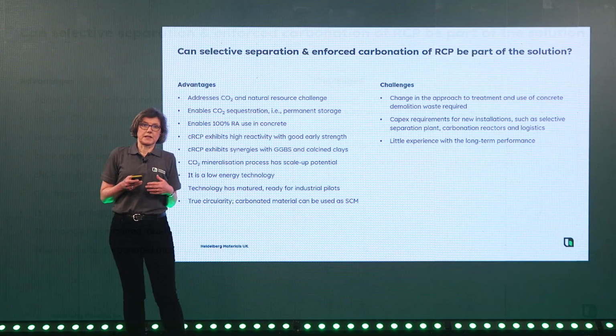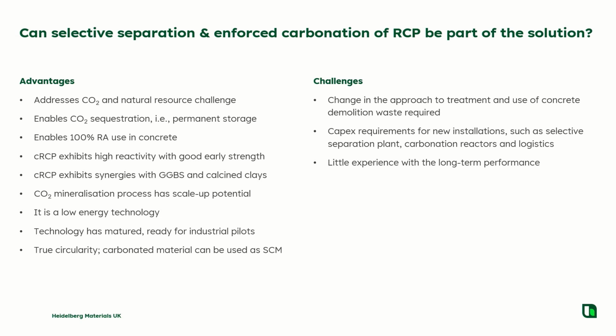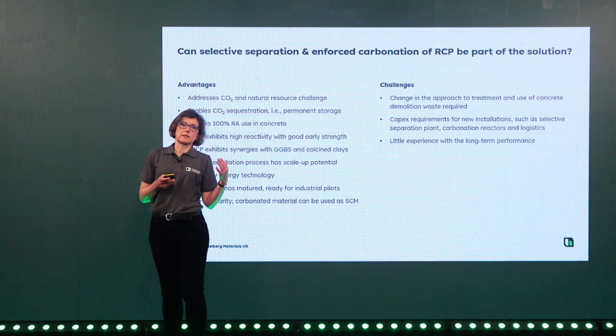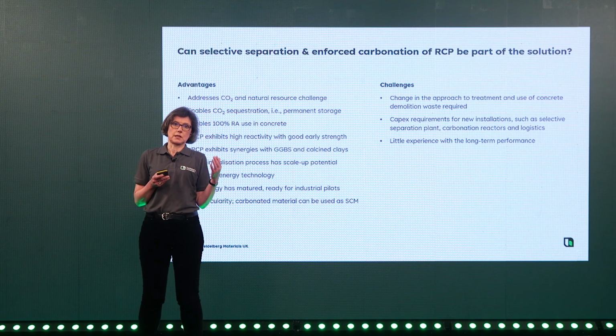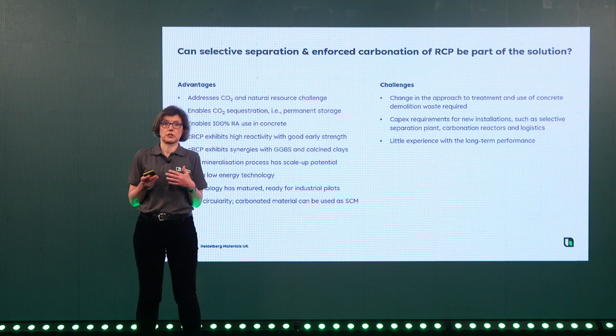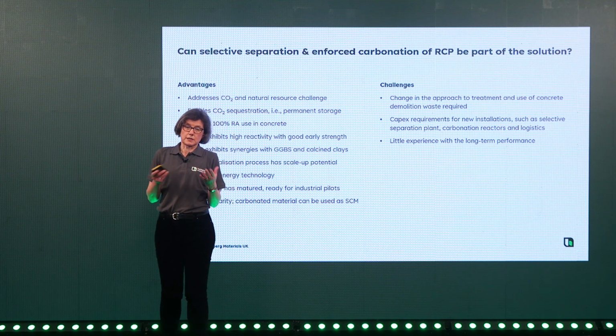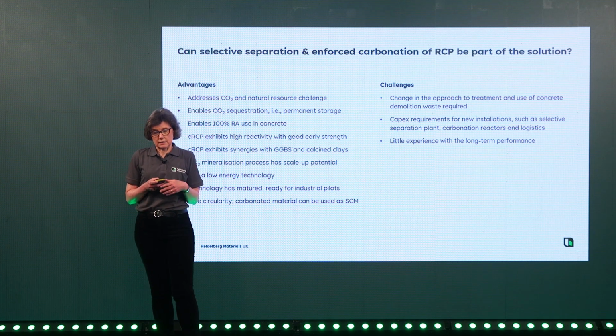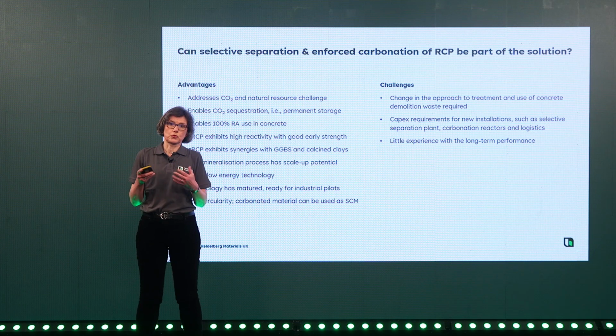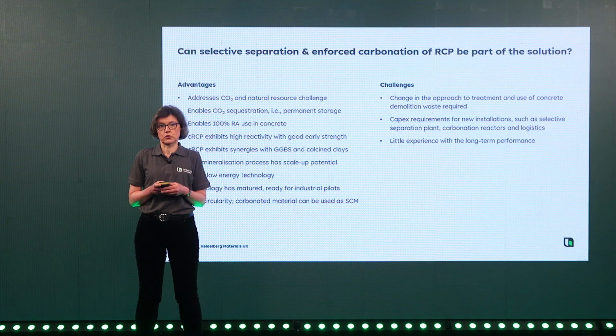So in summary, I hope I've been able to demonstrate selective separation and enforced carbonation. The advantages are really that it addresses both our challenges, the one of the CO2, but also having to maintain our natural resources by recycling. The process enables CO2 sequestration, which means permanent storage of the CO2, and the aggregates and the sand which we create in the process can actually be 100% replacement in concrete. The carbonated RCP exhibits very high reactivity with good early strength as well. And I haven't shown it in the presentations, but we have also done trials with mixes where we used CRCP and GGBS and calcined clays, and we get further synergies there, even better strength development. The process has the potential to be scaled up. It is a low energy process, and as you have seen, the technology is really now matured so that we can move to the next stages of industrial pilots, and it is an example of true circularity.